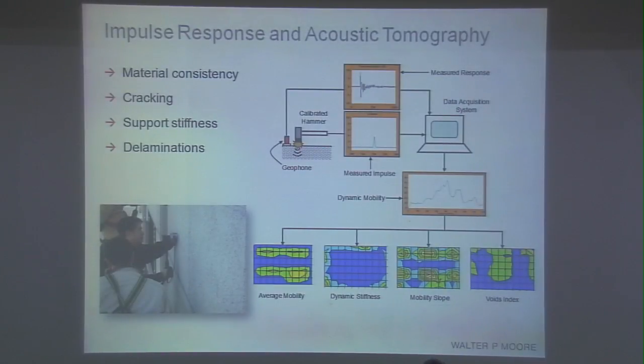I've included here also impulse response and acoustic tomography, which are two methods that are similar in nature, but work on different levels depending on whether you're looking at a mass concrete structure or whether you're looking at surface issues. But essentially the fundamentals are the same in that you're imparting a compressive impulse wave into the structure, and you're using an array of sensors to measure the arrival of that impulse at the receiving locations. By doing this iteratively over a matrix of points, you can plot different parameters such as mobility and stiffness within the structure based on the different arrival times of the signal to different parts of the structure.